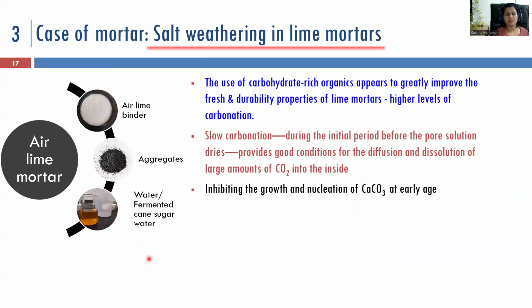The last case is of lime mortar, where we looked at the pore sizes and salt weathering impact. We had two different sets of lime mortar: standard ones with just lime, aggregate and water, and modified lime mortars with organic additives.